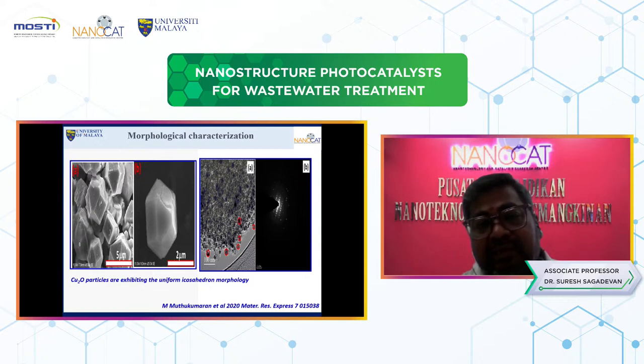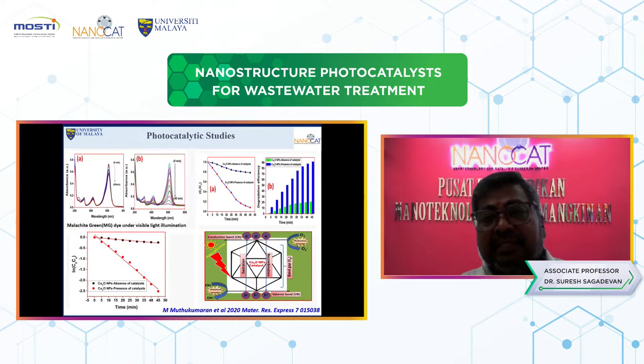And as well we did TEM analysis, where we can see the same morphology in the TEM image, highlighted here in red color. And as well the SAED pattern, selected area diffraction, where we observe bright rings, which means the material has a high crystalline nature, in good agreement with the XRD data. And then for this material, we tested only one dye, malachite green, because many people have done rhodamine B, methylene blue, and many dyes, but we tried a different organic dye.